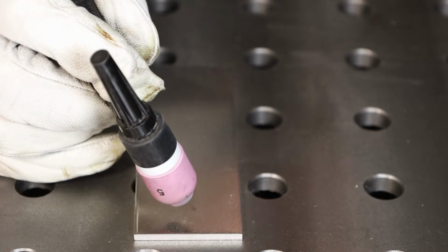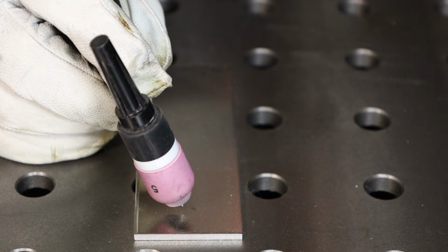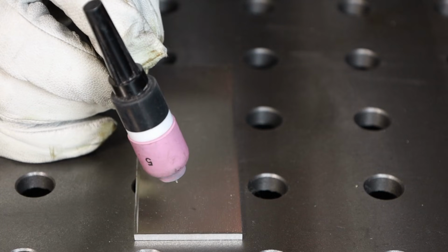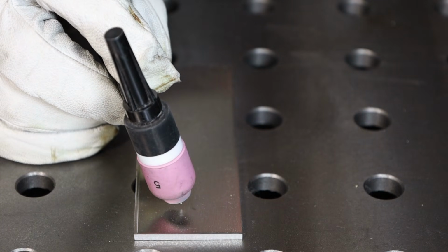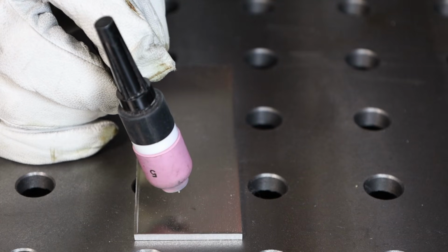So first, let's talk about your arc length, and this is the first thing to get down, right? When you go, you don't want to touch your electrode down to the material, but you don't want it to be too far away either, right? You're looking to be right in there. On aluminum, you can be about 1/16 of an inch, or let's see, what is that? About 1 to 2 millimeters away from your material on aluminum, and you'll be able to start to get a sense. You want to be in as tight as you can be without dunking your electrode all the time. So don't be way back there to avoid dunking your electrode, because you're not going to get the result that you want.